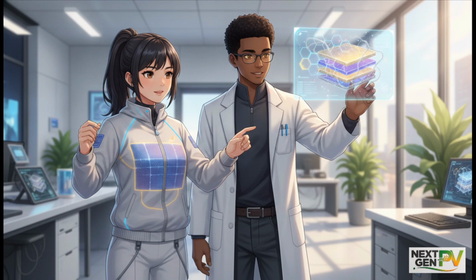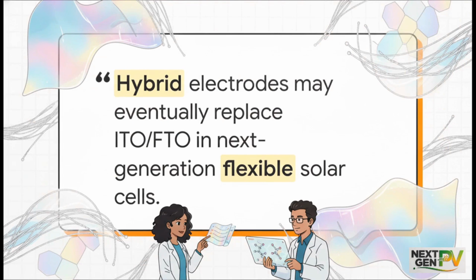To pull this off, researchers are aggressively moving toward hybrid electrodes, fusing the best properties of multiple materials together. Think combining graphene with silver nanowires, or putting a metal mesh together with a TCO. In fact, the expert consensus strongly suggests that this hybrid approach is the ultimate future of solar power. By laying down a highly conductive, flexible network, like silver nanowires or carbon nanotubes, and then coating it with an ultra-thin oxide layer, you solve the brittleness of ITO while also fixing the surface roughness of the nanowires. You get the best of everything: high transparency, low electrical resistance, and incredible mechanical durability, all in one single package.